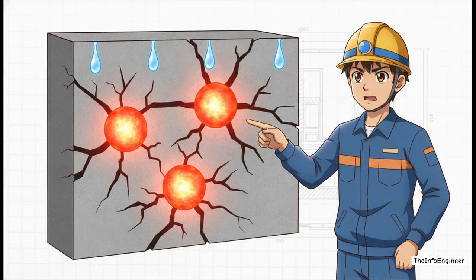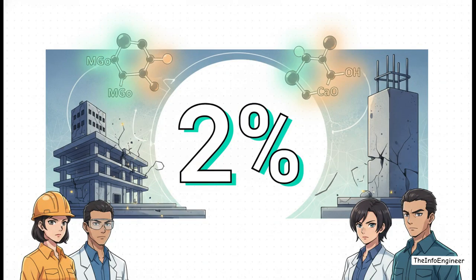And when moisture eventually finds its way in, that free lime slowly expands. It literally cracks the concrete from the inside out, making the cement completely unsound. This catastrophic delayed expansion is exactly why we have such strict chemical limits. For instance, standards dictate a maximum of roughly 2% magnesia, along with strict limits on free lime. By keeping our fuel ratios incredibly exact, we prevent that inner expansion and guarantee the long-term integrity of our buildings, ensuring they don't just crumble decades down the line.